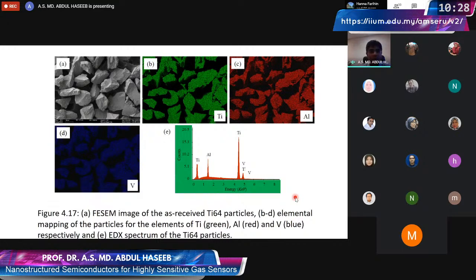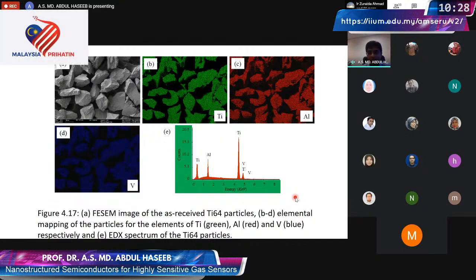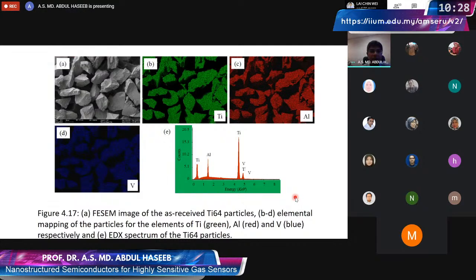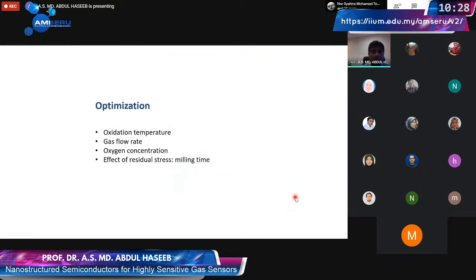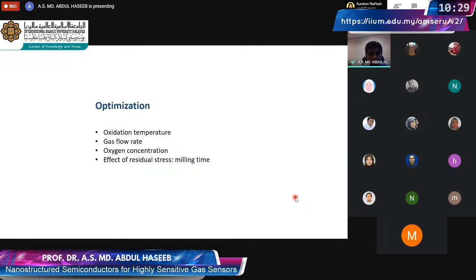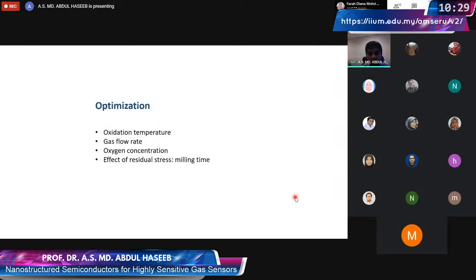And our motivation was that in addition, this alloy contains alloying element, particularly aluminum. And we have seen in the literature that when aluminum oxide is mixed with titanium oxide, the gas sensing property can be influenced. And this motivation was the basis for choosing this Ti64 alloy for our particular use. And once we have these commercial particles of Ti64, we looked at the effect of oxidation temperature, gas flow rate, oxygen concentration, effect of residual stress, because we also know that in order to grow a good nanowire, the residual stress inside can play a critical role. So we wanted to play with that as well.